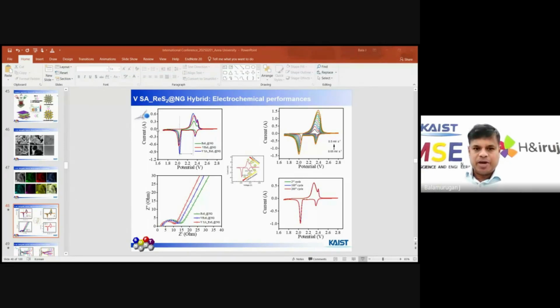When comparing to the rhenium sulfide nanoparticles, the vanadium single atom gives higher performance. You can see the blue one, the reduction and oxidation are very close, so the reversibility is very fast, with higher current density for both anodic as well as cathodic peaks. We also do different scan rates. When the scan rate increases, the oxidation peak shifts towards the positive direction, and the reduction or cathodic peak shifts towards the negative direction.